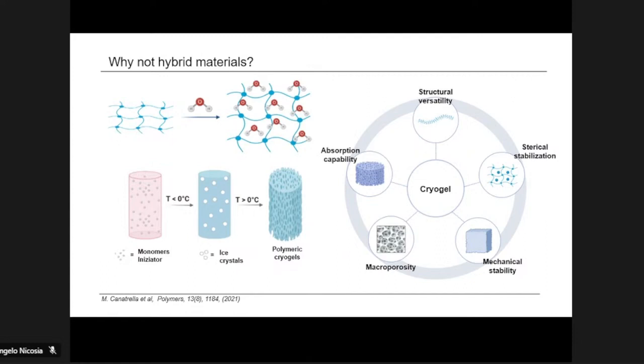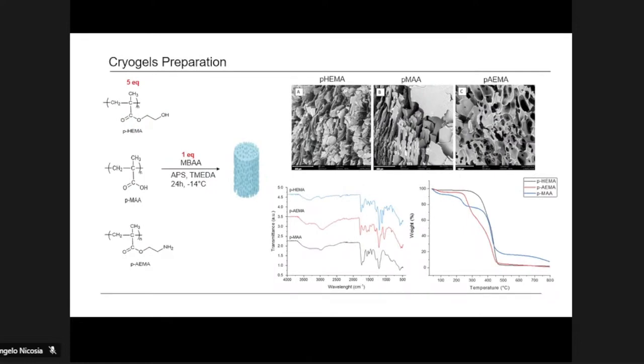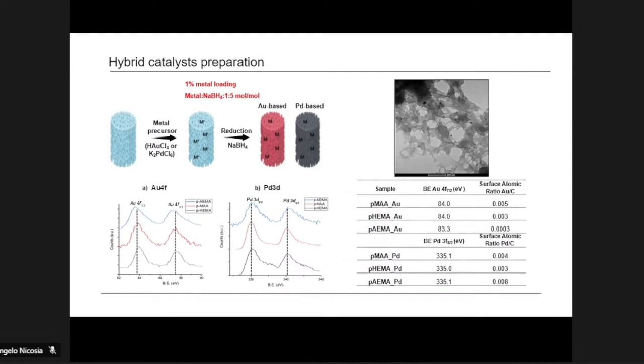In particular, we have prepared three types of cryogels with three different acrylic-based monomers characterized by several functional groups, with the presence of hydroxyl, amine, and acid groups, by a cryopolymerization reaction in the presence of a cross-linking agent to obtain the cryosponges. They were characterized by scanning electron microscopy, thermal analysis, and spectroscopy to confirm the material obtained. And at this point, by an in situ approach, we have an impregnation of the metal precursors, in this case gold and palladium precursors, onto the polymeric matrix, and then by a reduction step we obtain the nanoparticles directly inside the polymeric structure.